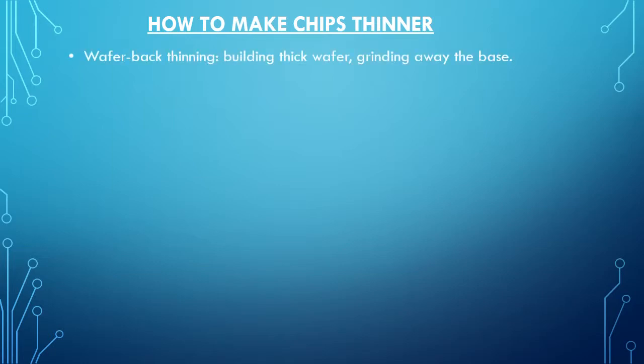The first and straightforward way is to make a conventional silicon chip and grind away the base. This can be done after the circuits are drawn on wafers and before they are diced into chips. Another way is to build a thin film of silicon on a layer of oxide which lies on a thick silicon substrate. These are called silicon on insulator wafers. The silicon is then removed selectively and uniformly.